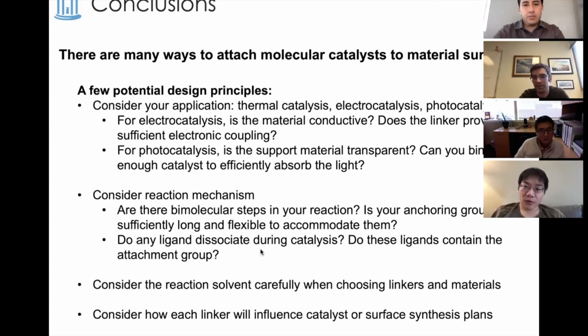Ligand dissociation steps can be problematic as well. For example, if you have your linker attached to the periphery of a ligand that dissociates during the catalytic cycle, that could be a problem from a stability perspective. I mentioned solvent a couple times here, and I think that makes a big difference in the choice of linkers and materials. And I would say that the synthesis matters a lot too, in terms of what a catalyst will tolerate as it's being functionalized for anchoring to a surface, and what kinds of functional groups are going to be compatible with the catalytic reaction later on. So those are some thoughts that might help guide people as they design systems like this.